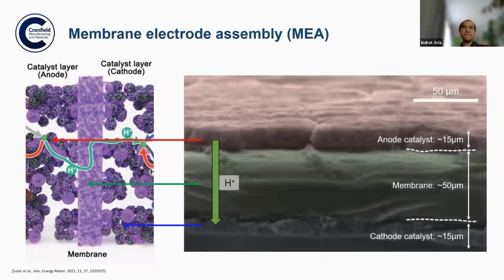If you look at the heart of the electrolyzer or fuel cell, you will find the membrane electrode assembly. This is basically a membrane sandwiched by two types of catalysts, the anode and the cathode catalyst. This is very thin. The membrane itself has a thickness of about 50 micron, and the catalyst has a thickness of about 15 micron each. But without this MEA, there is no fuel cell, there is no electrolyzer. This is the heart of electrolyzer or fuel cell.